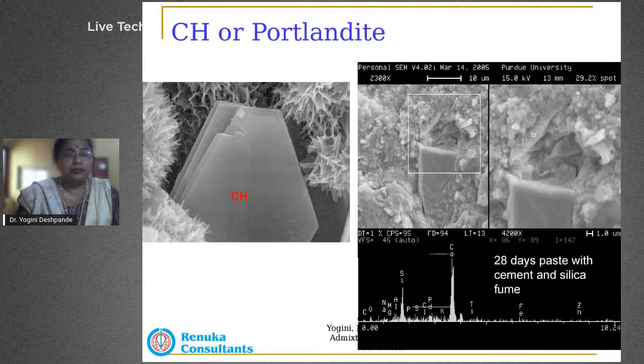This is much denser, as you can clearly see - this is at about 28 days with cement and silica fume. You see such a dense structure has formed, with just one plate of CH remaining - not unhydrated, but a slightly more permeable aspect of the hydration product - whereas a much larger amount of CSH is formed in the case of silica fume concrete.